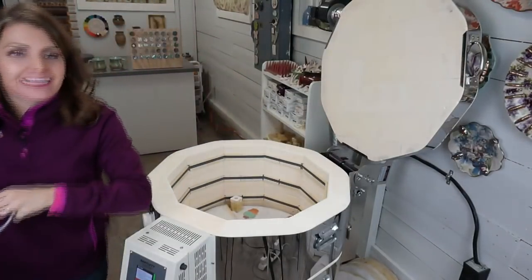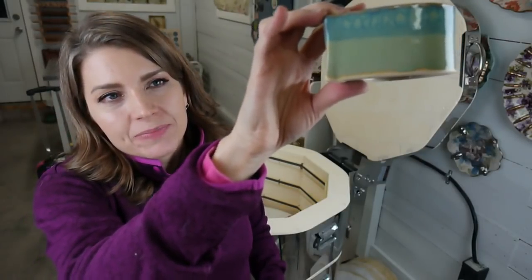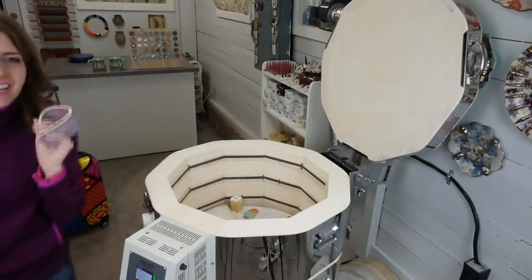These are a future class too. How thick do I roll out my slabs for cups? A little thicker than a quarter of an inch — by the time I flatten them with a rib and add texture, they're a bit thinner, and then they shrink in the firing. I'll show you the glaze: this is Amaco's Lavender Mist with Dark Flux — yummy! And then this is my Spearmint with my Lake Blue. This is how the spearmint should turn out — if it's not this beautiful spearmint color, it's too thin or too thick.